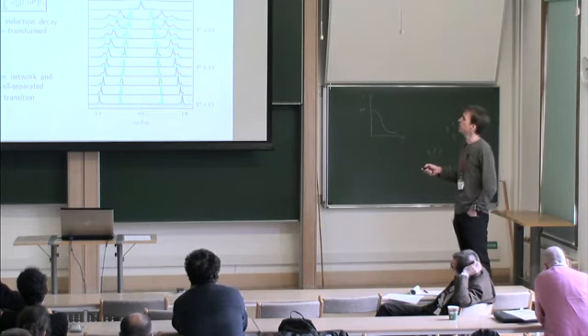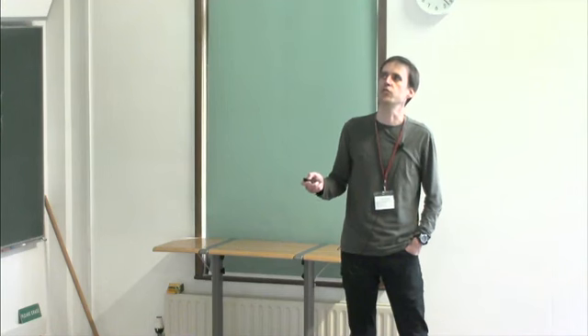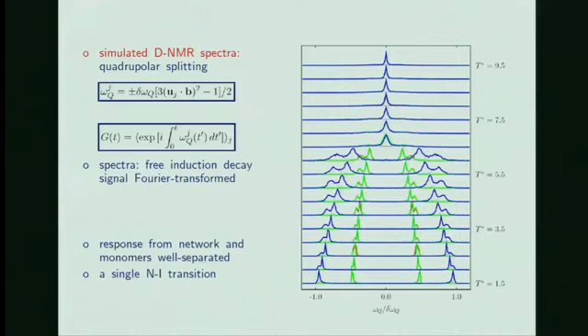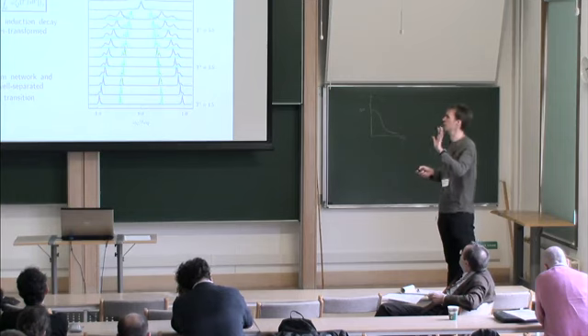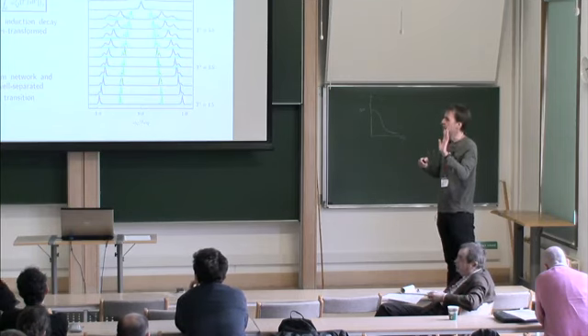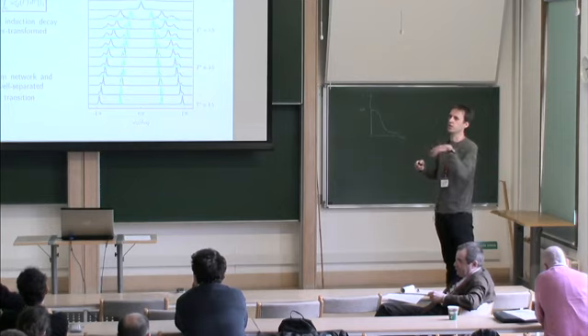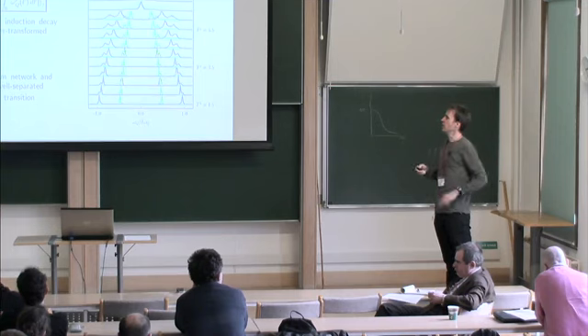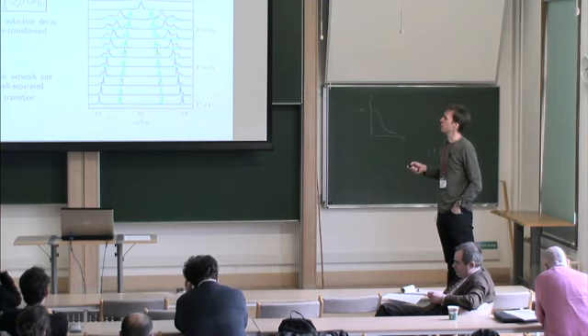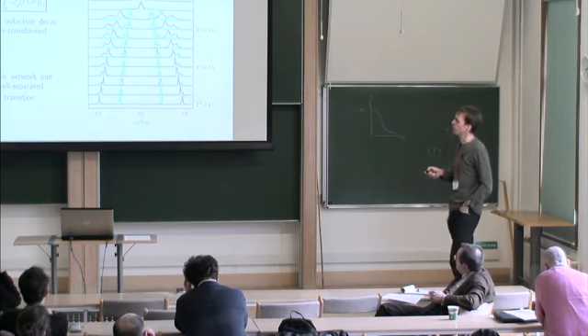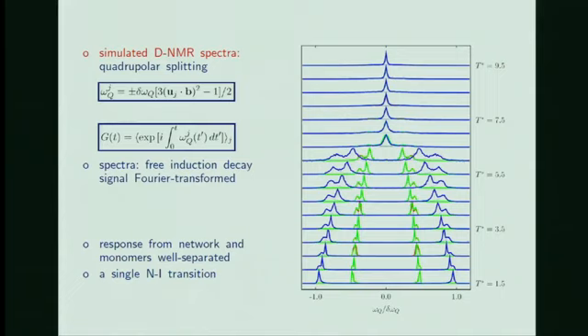And this is given by a P2 type dependence. So that's the long axis, and that's the direction of the field. And this is some coupling constant. So what we do here to get the spectra is we try to mimic an actual NMR experiment. If you put your sample in an NMR spectrometer, then you apply a so-called pi/2 pulse, your magnetization will start to precess, and then what you can detect is a so-called free induction decay signal, and then Fourier transforming it, you will end up with the spectra. So here we have a collection of these spectra from lowest to the highest temperature considered.